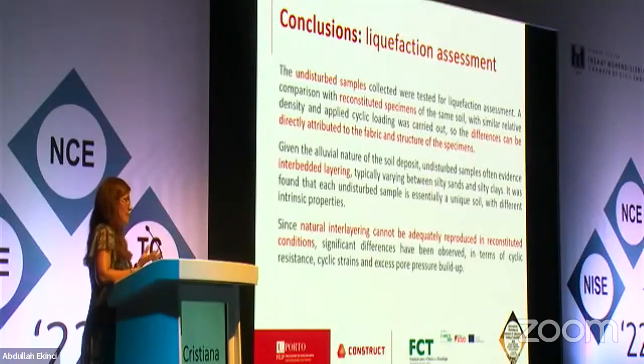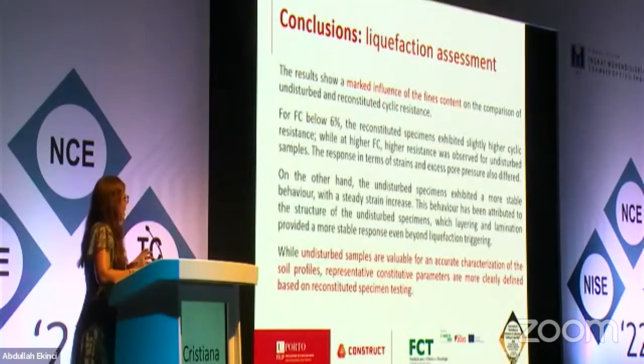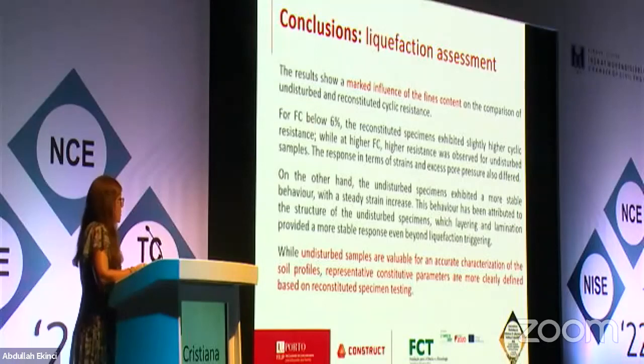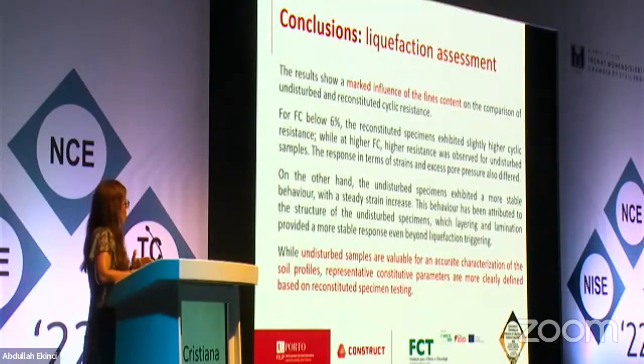Since this natural interlayering cannot be adequately reproduced in reconstituted conditions, we observe these differences not only in terms of the cyclic resistance, but also in the cyclic strains and the buildup of excess pore pressure. And the key parameter we found to be the fines content. So this really affected the comparison between the undisturbed and reconstituted.